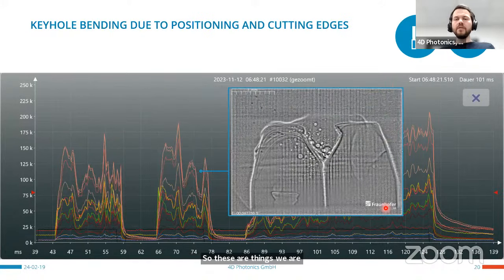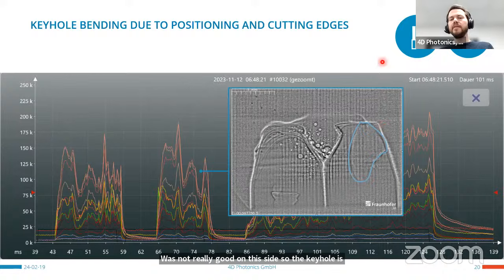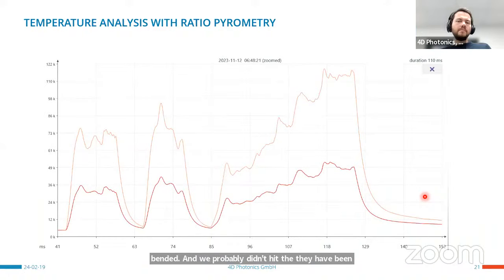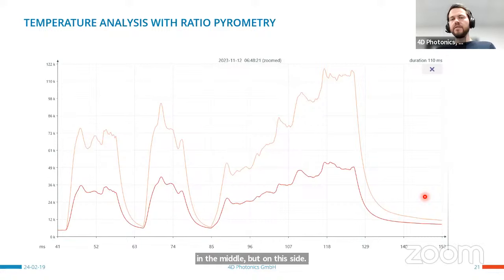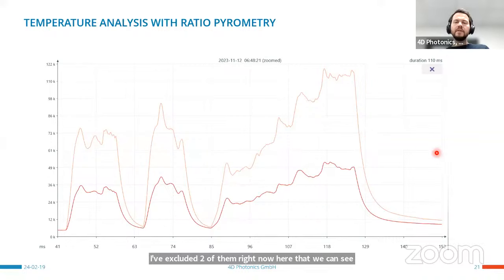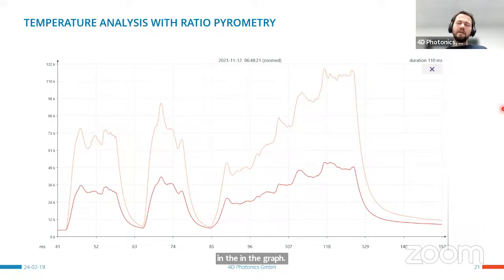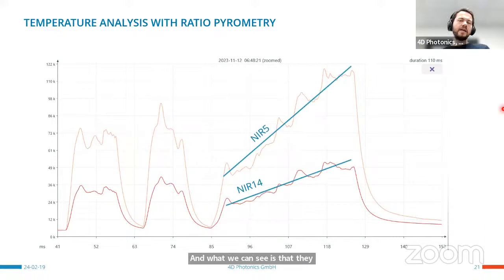We can also see the positioning was not really good on this side, so the keyhole is bent, and we probably didn't hit the hairpin in the middle, but on this side. Another thing we can do with the sensor is that we have a look at the near infrared channels. I have excluded 2 of them right now here that we can see in the graph. And what we can see is that they have a different gradient at the end.